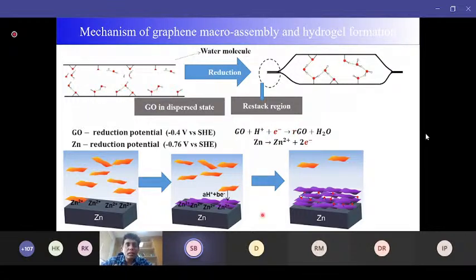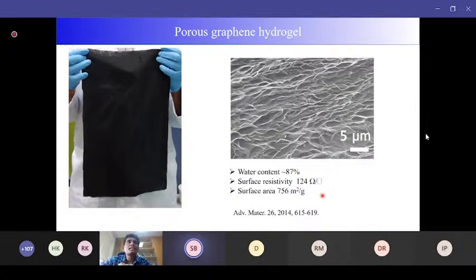And once this one layer of chemically functionalized graphene forms, another layer gets reduced, and they restack the way I discussed, but complete restacking is prevented by the hydrogen-bonded water molecules. So it leads to porous structures, where water is bonded in between the graphene layers, so that we can get this kind of structure. This is the hydrogel structure.